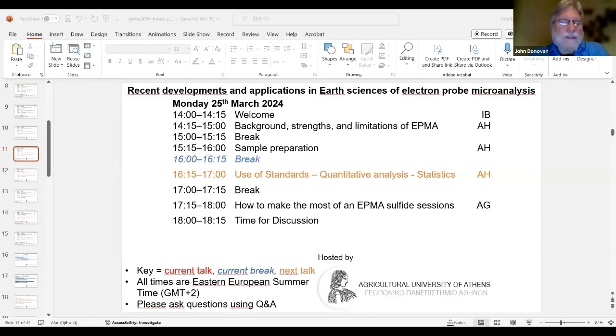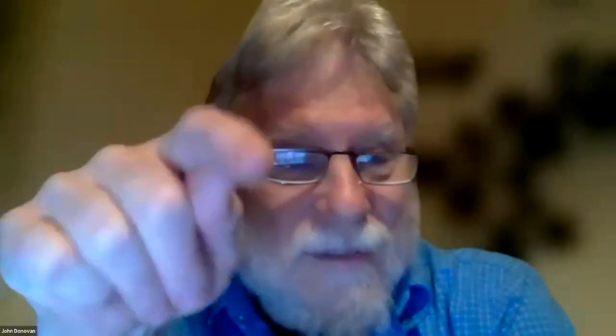Especially because, for example, when I analyze standards, I typically will measure n number of points just with an X offset. And since the X offset is in a line, you wouldn't be able to do a tilt correction on the standard. So it's certainly something to keep in mind, but it's not a cure-all, and it certainly doesn't deal with any surface roughness issues. That is something that you just have to fix in the polishing sample prep steps.